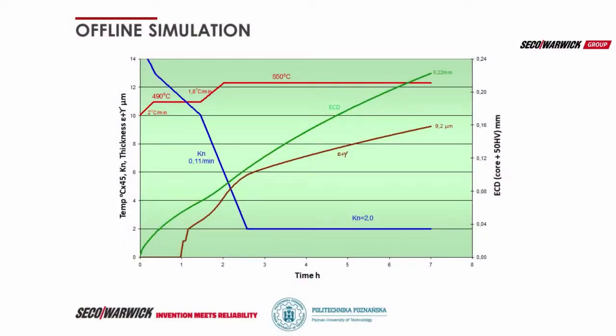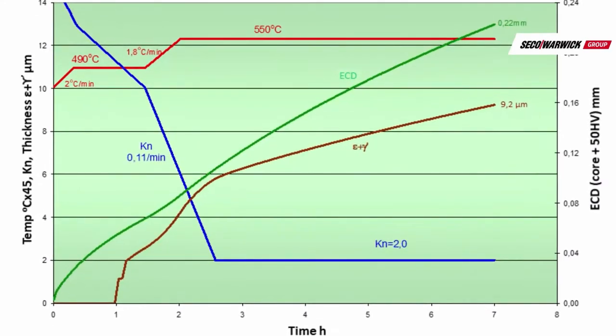This graph depicts a simulation of a process with arbitrarily set values of temperature, which for the first stage is 490 degrees Celsius and for the second stage 550 degrees Celsius. Heat-up speed to the first stage temperature is 2 degrees Celsius per minute and to the second stage temperature 1.8 degrees Celsius per minute. Nitriding potential in the first stage equals 10 and in the second stage equals 2. Speed of reduction of nitriding potential from the first to second stage value was set to 0.11 per minute.